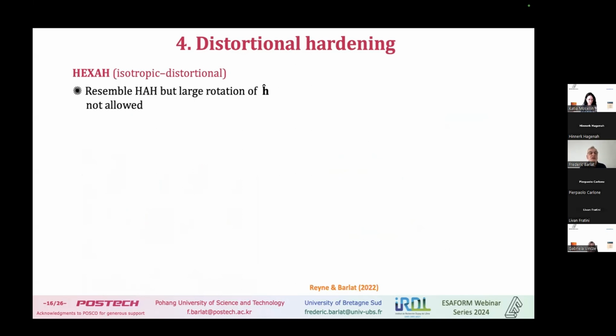Okay, so now I'm going to talk about still an approach based on isotropic distortional, but we call it HEXAH, and it's the most recent model. It's a little bit like HAH, but we don't have large rotation of the yield surface when we change strain path, as I showed you before. One of the reasons is it's difficult to capture the coefficients correctly when we have this rotation. We noticed that. And it's difficult to represent exactly what we want, because the rotation is kind of a difficult concept to handle.